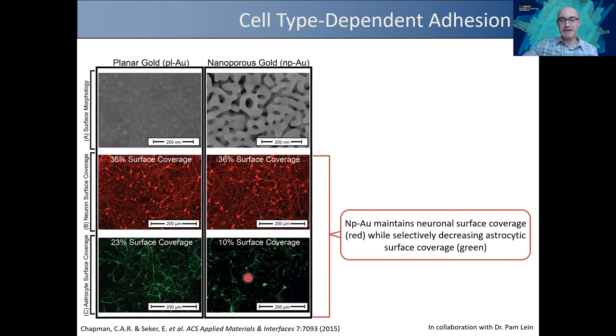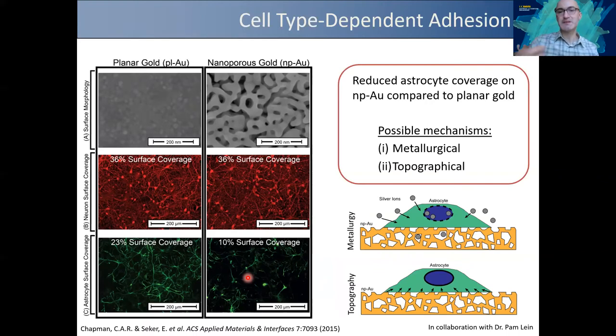However, we had to play the devil's advocate and be skeptical and ask the question, is this really the topography or is there a metallurgical component? Remember, the way we make nanoporous gold is you leach the silver out. So perhaps there is some residual silver leaching out, and astrocytes are sequestering it, and it's basically reducing their viability. So in order to test this, we need to somehow rule out the potential of the silver leaching out.